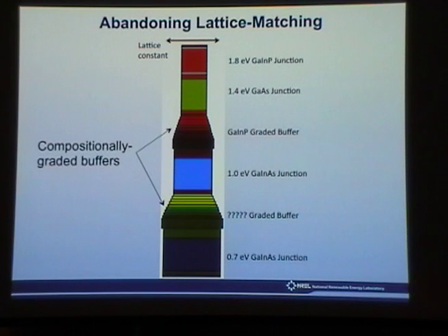But why don't you use the amorphous materials? So we got lattice constants problem. So for example, what's an example of an amorphous material? Like ITO. Yeah, so they're not necessarily the same. They don't have the same material quality. You can get much better material quality and higher voltages out of the III-Vs, and it's a material system that allows for all these alloys to be grown at the same lattice constant.